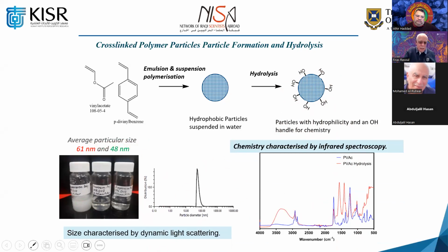We measured it using dynamic light scattering. You could see the size of the particles between 61 and 48 nanometers. So they are on the nanometer scale. And this is really useful because if you try to inject this into a well, for example, a formation in rocks, it will be easy to pass it through and move to the other side. And even if you use it for other applications, it could be used really easily. The only problem we were facing with this material, because it's an organic nanoparticle, is that even though it's cross-linked, we are not sure whether it sustains higher temperature applications. So we looked into that, and alternatively, we looked into solid nanoparticles, like silica and ferric oxide and others. Okay.